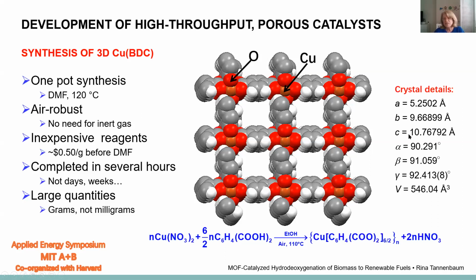And here we have some details about the crystal structure that we get. What we end up with is a one-pot synthesis. You put these things together, and it's very easy to do. This is done under air. There's no need for inert gas. These are inexpensive reagents, and this is done in DMF. The reaction is done in a few hours, and one can have very large quantities of this material.